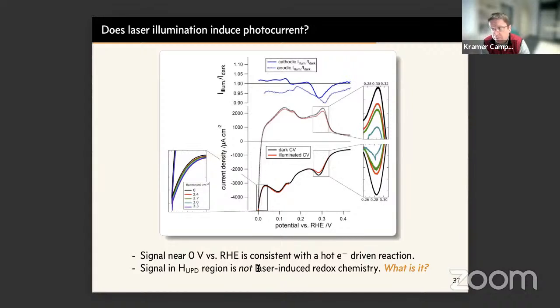Okay, so we're not so clever, right? We tried to start with the simplest possible experiment we can imagine, and we leave our laser unblocked. So this produces now a pulse train of about 40, 50 femtosecond pulses with a wavelength of 800 nanometers, and they arrive at the electrode every millisecond. And now we just collect a voltammogram. So this is what is shown here for a platinum microelectrode. The CV in the dark is shown in black, and the CV in red is under illumination, right?